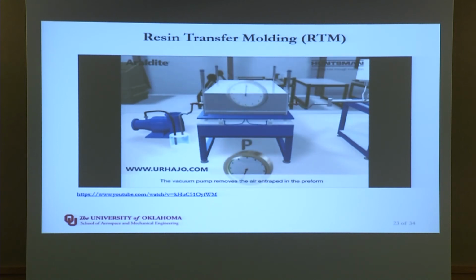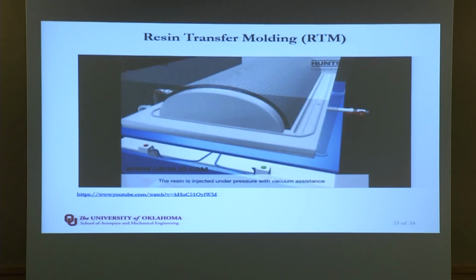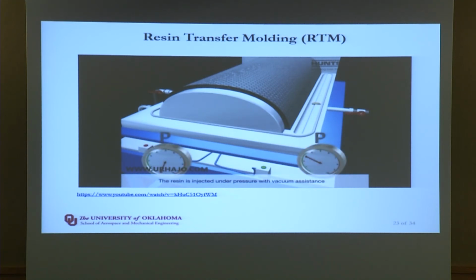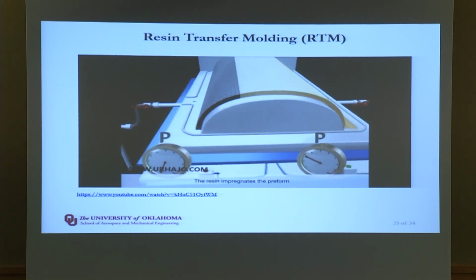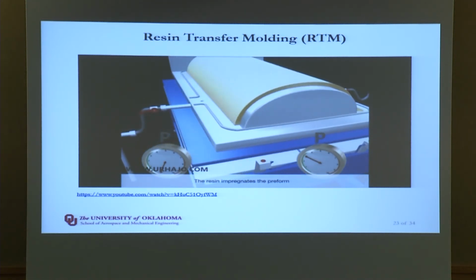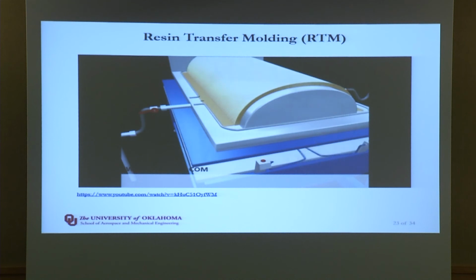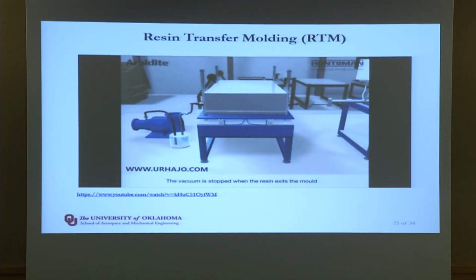So you have the pump. This is a combination of vacuum and an injection. So you pull vacuum and then you essentially inject under pressure. Yep, so the resin is coming in. Of course, this is inside the mold, right? All right, it's going up. And then this is a closed mold. All right. So vacuum is stopped. When you see the resin is coming out from the exit, you let the part cure.